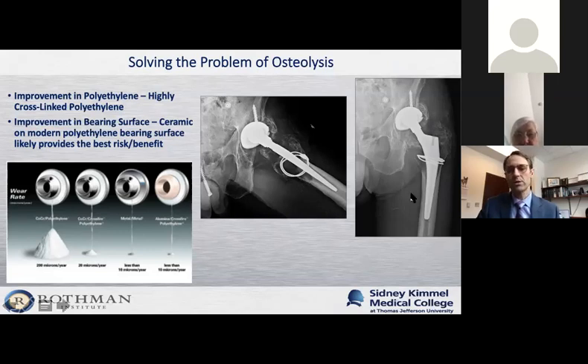Pictured here is a patient that I've taken care of that has a significant amount of polyethylene wear, and we know that because when we implant these, the ball should be sitting very centered within the metal shell, but you can see here that the ball has worn up and out and is sitting much closer to the top part of the shell than the bottom part of the shell. Then secondly, this patient has experienced a significant amount of bone resorption in the top part of their femur, whereby you can see the difference in the density of the bone down here versus up here, higher up where the patient has had this debris lead to this localized loss of bone.